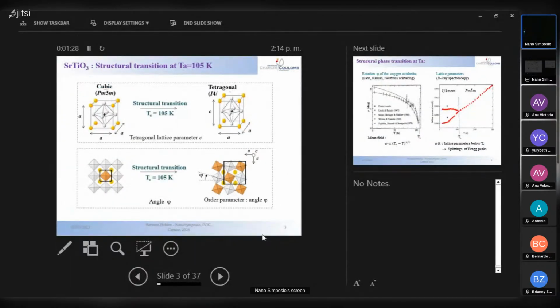Okay, so a bit of history of this compound. Strontium titanate exhibits a structural transition at the temperature of 105 Kelvin from cubic to tetragonal. In the tetragonal form, you have the growth of the C tetragonal axis. The square cubic frame develops a C tetragonal axis. But in addition, if you look at the top of this structure here, you see the octahedra, and the octahedra rotate in antiphase, one octahedron one way, the other one the other way, and so on. You have an angle phi which develops at the same temperature. And this angle phi, by the way, is the order parameter of this transition. It is 0 above 105K and non-zero below 105K.